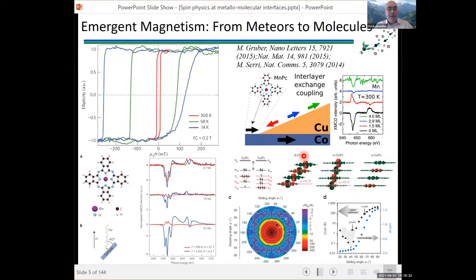You could go from paramagnetic to antiferromagnetic, so you could have an exchange that could be negative or positive with different magnitude depending on the angle between the molecules. So they see this as a means to engineer the magnetic properties of your thin film depending on the growth conditions, temperature, substrate, annealing, and so forth.